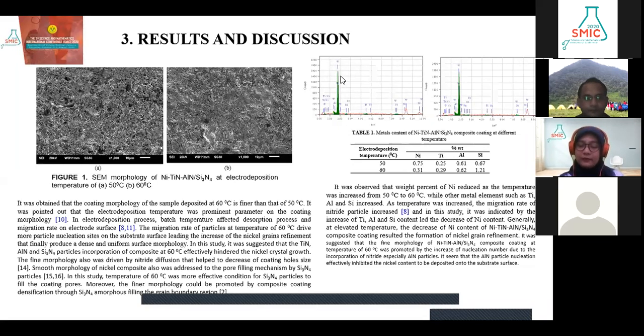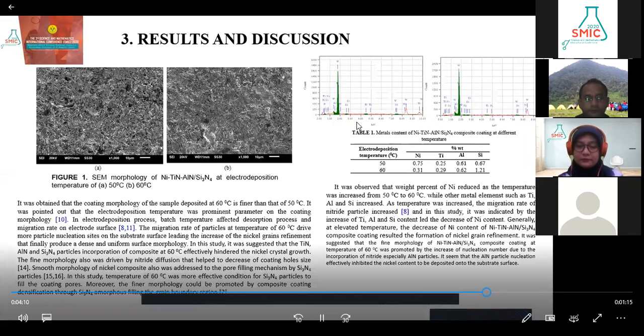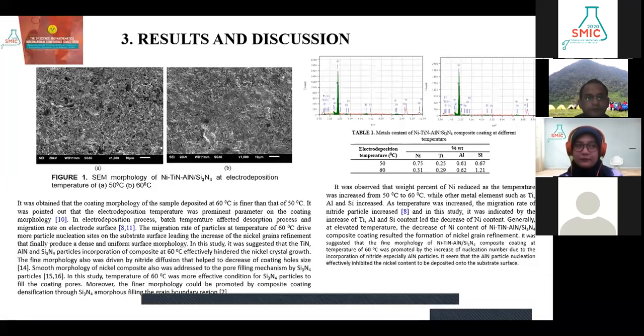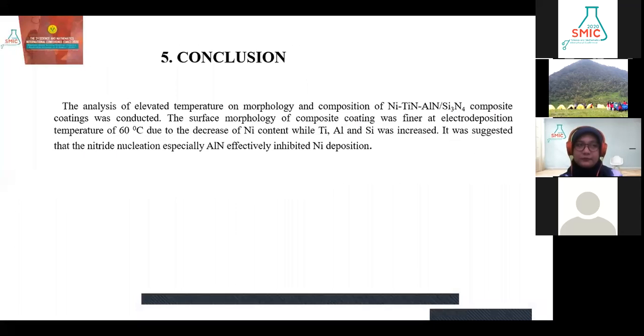From the composition analysis by using EDS, it was observed that the nickel content reduced as the temperature was increased, while other metal particles such as titanium, aluminum, and silicon increased as the temperature was increased. Generally, at elevated temperature, the decrease of nickel content in the composite resulted in grain refining. So the conclusion of this study is that the analysis of the elevated temperature and morphology of the composition of Ni-TiN-AlN/Si3N4 composite coating was conducted.